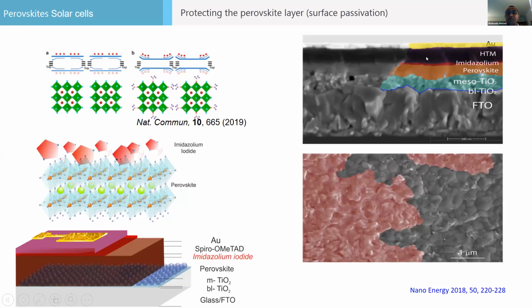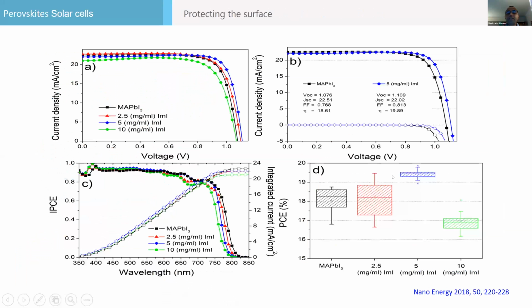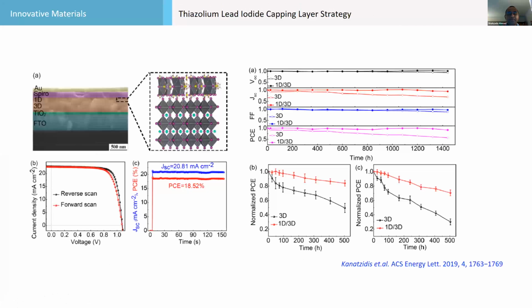A very thin layer of imidazolium iodide was placed on top of it, and that time also we have increased. We have seen a jump in the efficiency from 18.6 to 19, almost 20% efficiency, I think 3 years back here. Then another molecule we were working on, thiazolium iodide.